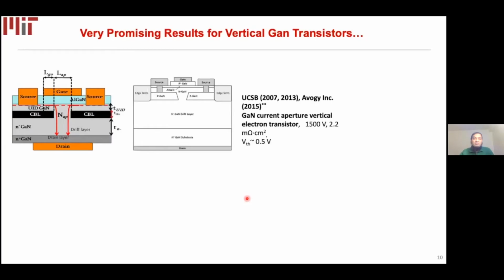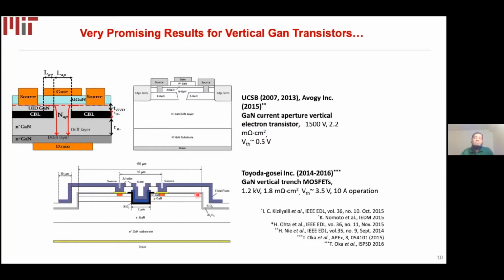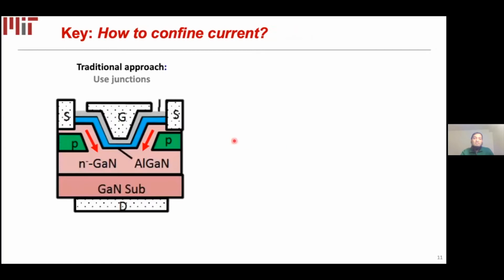And there has been a lot of work in the community on vertical GaN transistors over the years. The two most common approaches are the current aperture vertical electron transistor and the trench MOSFET architecture. In both of these technologies, our colleagues around the world have shown very promising performance, with a breakdown voltage up to 1.5 kilovolt and a specific on-resistance down to around 2 milliohm centimeter squared. Both approaches rely on developing a novel junction. For example, here we're showing a typical architecture of a vertical GaN transistor, where we have a p-type gallium nitride region that helps to form a junction with the n-type GaN and helps to confine the current.